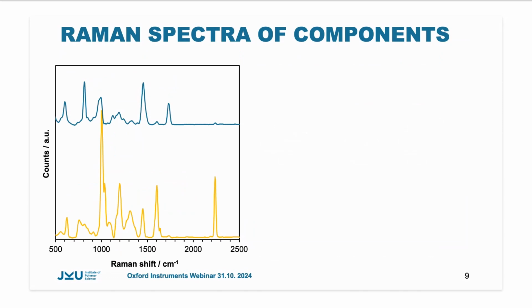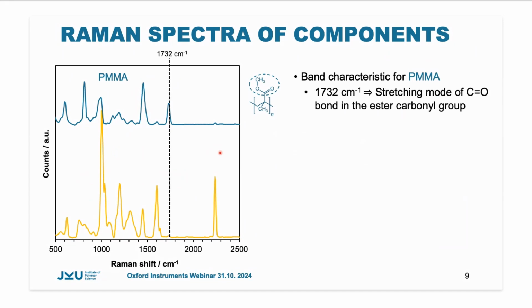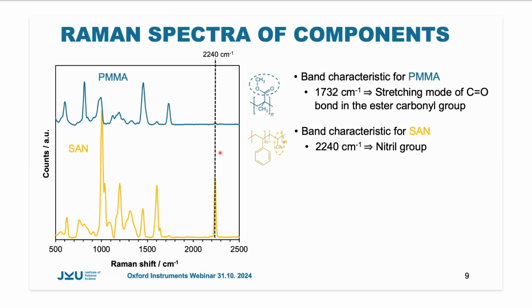The Raman spectra of our components look like this. We have the fingerprint region where we find for the PMMA one band which is characteristic at 1732 reciprocal centimeter, which can be assigned to the stretching mode of the carbonyl bond in the ester group. On the other hand, we have the SAN. Here we also have one band which is characteristic. This is the band at 2240, which can be assigned to the nitrile group.